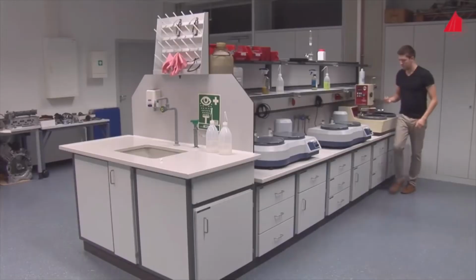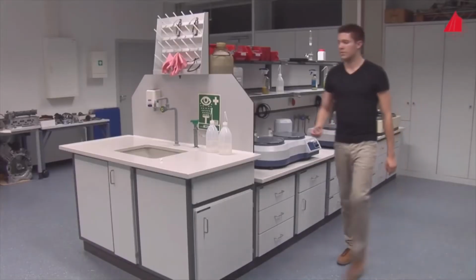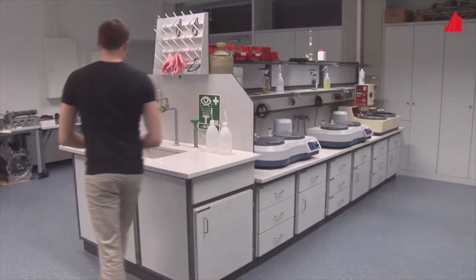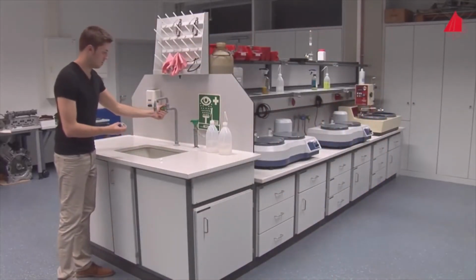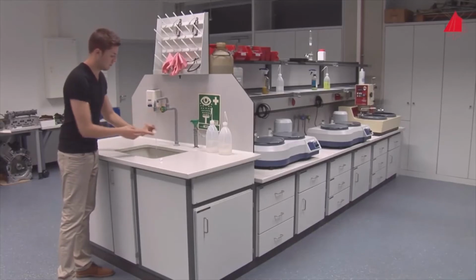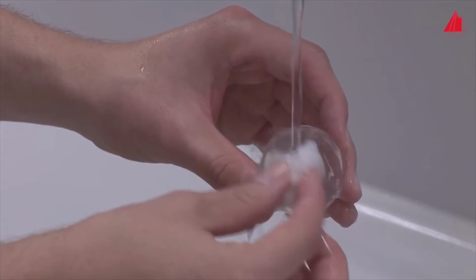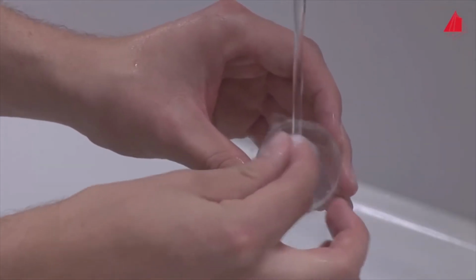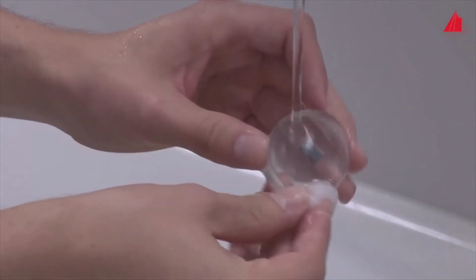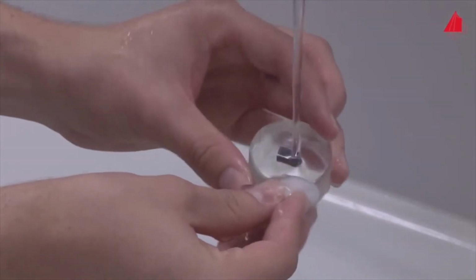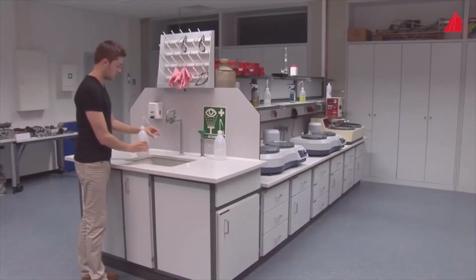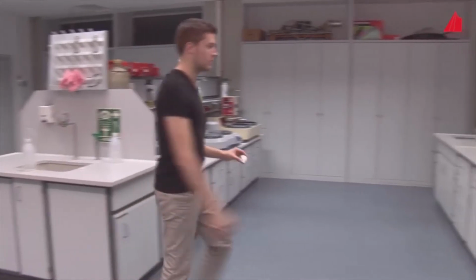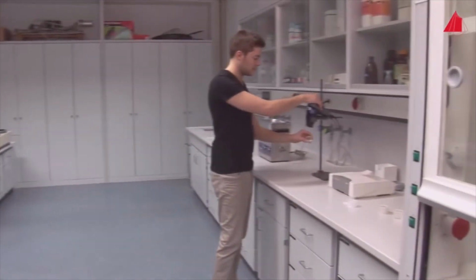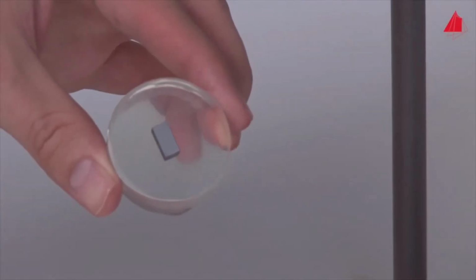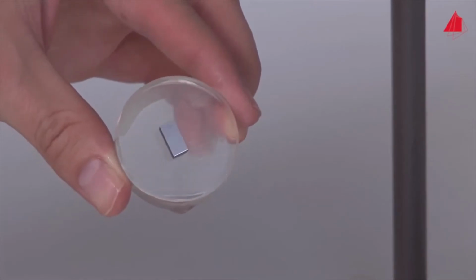At the end of the mechanical preparation, special care has to be taken to clean the specimen properly. On the one hand, all abrasive particles have to be removed. On the other hand, the freshly polished surface must not be scratched or damaged. Under running water, the material tester gently wipes the specimen with cotton wool, thoroughly rinses it with alcohol, and dries it with a hairdryer. From now on, the sample is called a metallographic specimen or microsection.